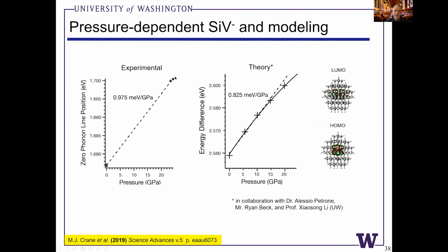We just made the pressure-dependent ZPL measurements, and there's a shift of about 1 milli-electron volt per GPa, and this agrees very well with some other very nice measurements reported recently in the literature using materials grown in a multi-anvil press. And then we compared our results, about 1 meV per GPa, with Xiaosong's calculations. They just used the lattice constant pressure dependence of diamond to make calculations of the ZPL pressure dependence. And their prediction was about 0.8 meV per GPa, just about 1 meV per GPa. So for a collaboration between theorists and experimentalists, this wasn't that bad, considering the assumptions we had to make. We had argon atoms throughout our lattice, and surface reconstructions and a number of things that can shift the ZPL, or internal strain effects. But Xiaosong's group did a great job just in terms of blind calculations. We're very pleased to see their agreement with our experiment.